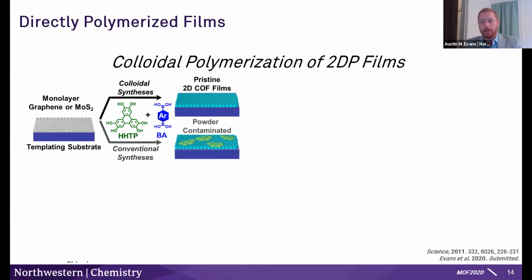But really, the colloidal suspensions themselves are not really amenable to devices, at least not directly, because it's hard to imagine a device geometry where a piece of that component is going to be a liquid, right? But going back a few years, the Dichtel lab had realized that if you immerse a flat substrate that can have van der Waals contact with the 2D COF, the COF will actually form a nice film on this templating substrate. So that could be graphene, MoS2, lots of other two-dimensional materials that have these high amounts of van der Waals contact with our 2D polymers that we're going to make here.